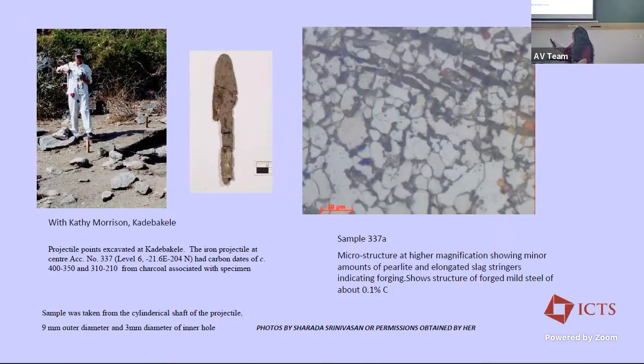So this is to point out some of it. I had pointed to this site, Kadebakele, where we found very early higher carbon steel. And of course, this is just to show you what normal mild steel or wrought iron would look like. You see the normal ferrite phase. And what I was trying to tell you with the sample that I already showed you is that it had much more of the pearlite phase and almost no ferrite. So that is how you can tell a high carbon steel from a low carbon steel or wrought iron. What you're seeing here is more along the composition of what you would find in the Delhi iron pillar, with the slag stringers and so on.